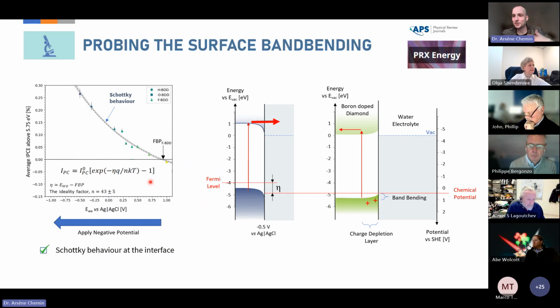So as I said, you can consider the diamond plus the electrode as semiconductor and metal, and indeed, the diamond interface behaves exactly like a Schottky diode. A very bad one, actually a very terrible one, because if you look at the ideality factor in the behavior, it's actually huge. So it has a lot of defects, of course, but the description and the mechanics behind it are exactly the same. When the photocurrent is zero here, it's what we call the flat band potential. It's basically the potential at which the band is completely flat, leading to no particular preferential direction for the photocurrent.